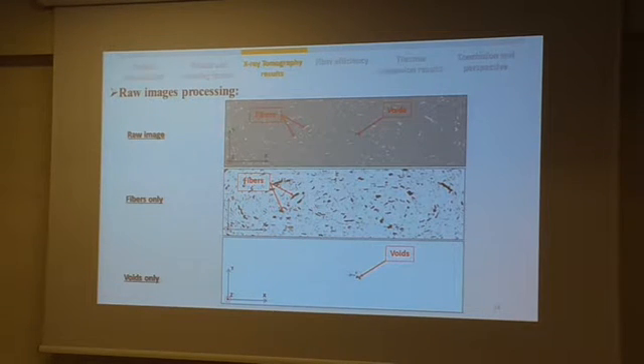So X-ray tomography result is presented in form of raw images. In these raw images, we can see the different components of the composite: the fibers, the polymer matrix, and also the voids. So, processing these raw images, we can isolate fiber only or voids only, depending on what we want to see. And we can do a 3D reconstruction of fiber distribution or void distribution also.